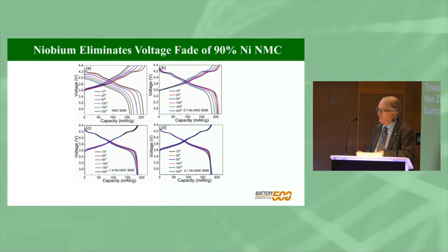So here's the data for these 4 different, 0 niobium to 2% niobium. And you can see here's the capacity fade continuously occurs from the beginning to the 200 cycle, a little bit less with 0.7 niobium. And by the time we get to 2% and even at 1%, you can see now there's no capacity loss at all. So this niobium is really stabilizing that lattice, which means that niobium in our mind is stopping that diffusion of the oxygen, so the oxygen cannot be evolved at the surface, so you can't form these so-called rock salt phases at the surface. There's no question that niobium is helping.